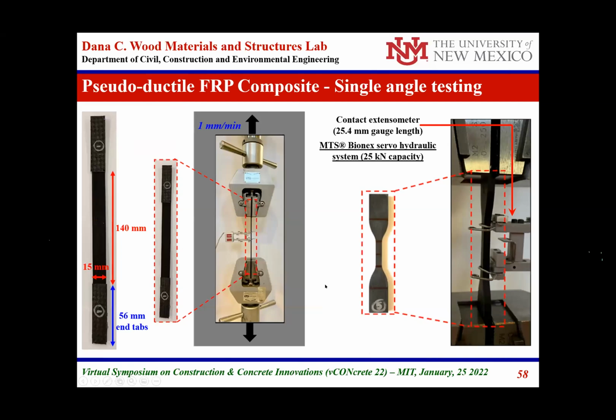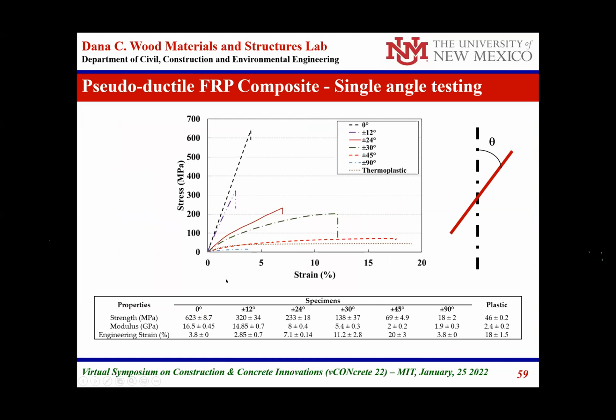So this is the tension test of the FRP that is 3D printed. What we tested first is the layers of the 3D printed FRP - this is just the material at 0, 12, 24 degrees, the angle we're talking with the vertical - and this is the behavior of the FRP printed material and the thermoplastic itself, the polymer matrix. At the different layers, we got the strength and the modulus of each one of them.